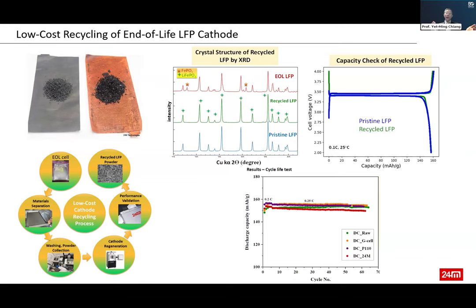Now, if we were to ask, what is wrong with the carbon, the graphite anode, and the LFP cathode now at the end of life? I would say that what's wrong is that we've transferred some of the lithium irreversibly over to the anode. So we have SEI there of primarily lithium carbonate. We've lost some of the lithium, therefore, in the cathode. So it's a little bit deficient in lithium. And there are probably pretty widespread crystallographic defects that have been formed in both these active materials.